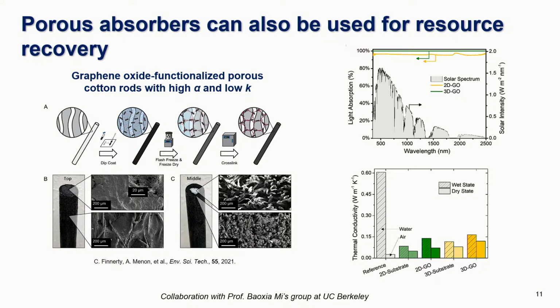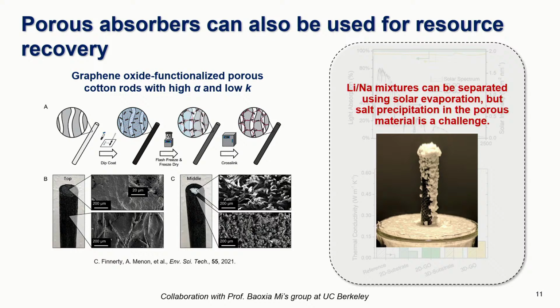So this is a collaboration with UC Berkeley, and we're looking at how can we functionalize this graphene oxide further to do additional things such as selectively recovering lithium from a lithium-sodium brine. And so these are some experiments that we've been running recently, looking at if you have a small amount of lithium in a predominantly sodium solution, can we get spatial separation of the lithium from the sodium across the radius? And so we're seeing that because of solubility differences, we're able to concentrate the lithium while most of the sodium precipitates out like this. And so this is one project where we're looking at trying to further optimize the lithium selectivity and extraction using just this passive solar evaporation system.